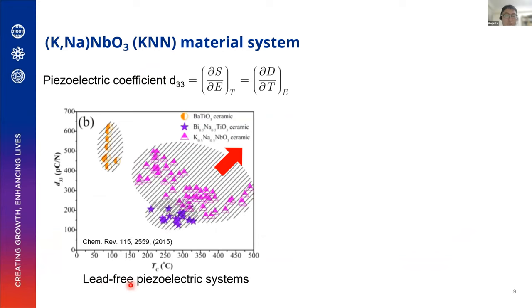The most well-known conventional piezoelectric thin film material is lead zirconate titanate, PZT, but because the lead content in the material is very high, it is going to be banned by regulations like those of the EU. So people are developing lead-free piezoelectric materials. These are the three major lead-free systems. Potassium sodium niobate is one of the leading candidates because of its high piezoelectric coefficient and high Curie temperature.